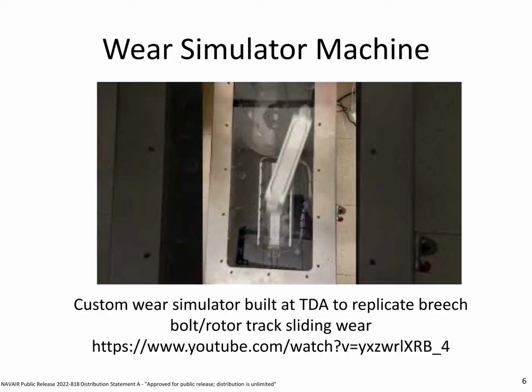This is a picture of the wear simulator that we built at TDA. You can see the simulator in action if you go to the YouTube link on the bottom of this slide. It's built to replicate a breech bolt and rotor track or slide rail sliding wear. We machined pieces based off of the exact dimensions of the breech bolt body and rotor track used in the M197 gun. We coat them and we hook it up to this simulator, and you can set the temperature, you can set the number of cycles that you want it to run. So there are 3 chambers to this gun, so 15,000 rounds divided by 3 would be 5,000 cycles, and that's where we get those numbers from.